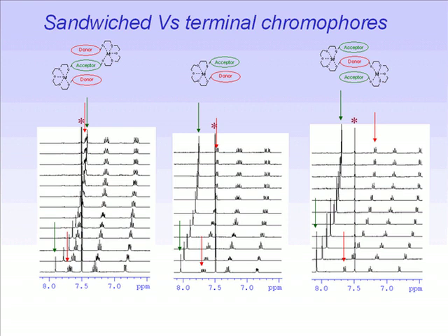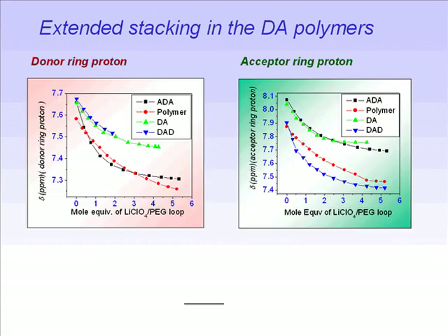So we can modulate the extent of interaction in these cases by the presence of metal ions, as very clearly evident in these spectral signatures. In the presence of an appropriate alkali metal ion, it constrains the conformation of the loop, thereby bringing these two in right registry so as to be able to form these interactions that give us signals spectroscopically, as well as lead to folded conformations of the polymer.